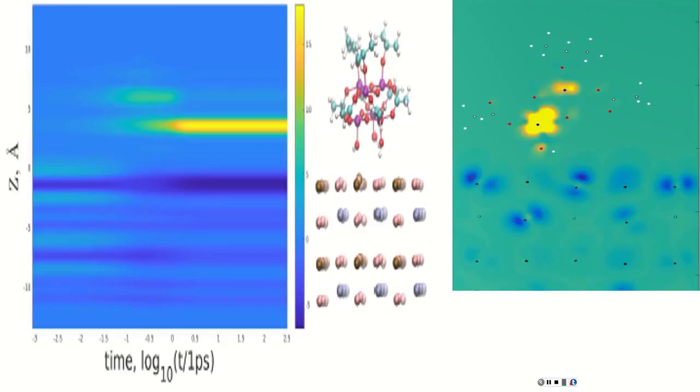Good question, and the answer does exist. The edge of the conduction band is originating from titanium, not from oxygen, right? Yes. If you do have only titanium dioxide in your simulation cell, your conduction band is composed of titanium 3D, and the valence band is composed of oxygen 2p. So if you do project PDOS, there will be no oxygen-related orbitals in the conduction band.